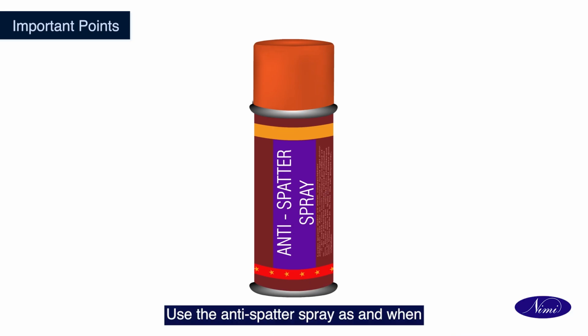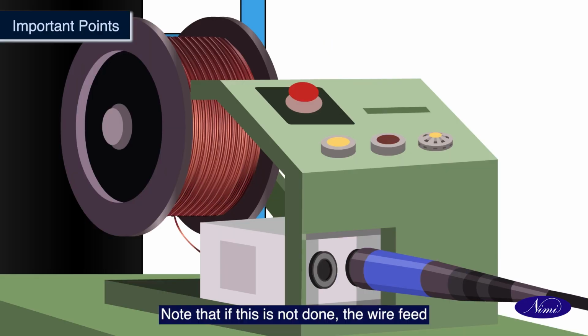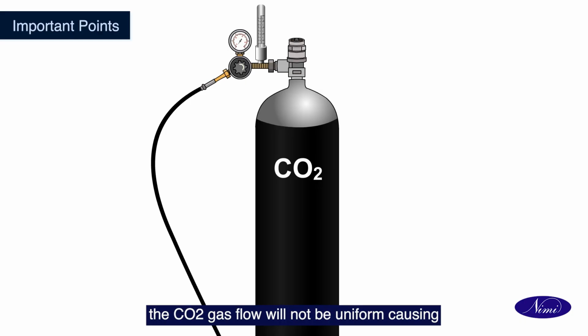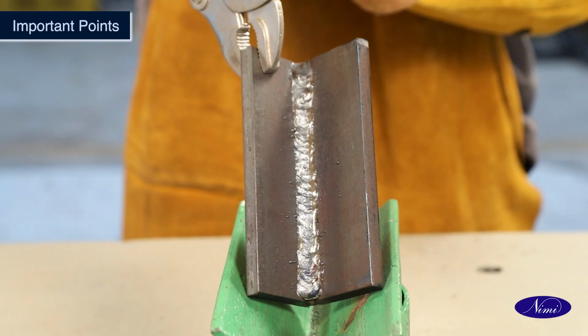Use the anti-spatter spray as and when the torch nozzle gets clogged with weld spatters. Note that if this is not done, the wire feed may be irregular, causing unstabilized arc, and the CO2 gas flow will not be uniform, causing atmospheric contamination of the weld and porosity.